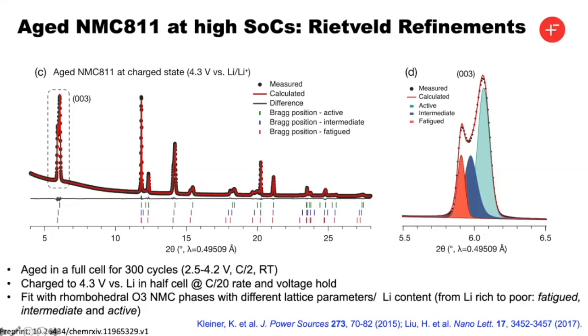three different rhombohedral patterns. So there's no evidence for any O1 phase. Everything is the normal rhombohedral structure, but it's clear that there are multiple c parameters. And so we're just going to distinguish between them as three different components, that being the minimum needed to fit the patterns: the most fatigued phase, the intermediate phase, and the so-called active phase that looks very much like it does the same thing as the material in the first cycle.